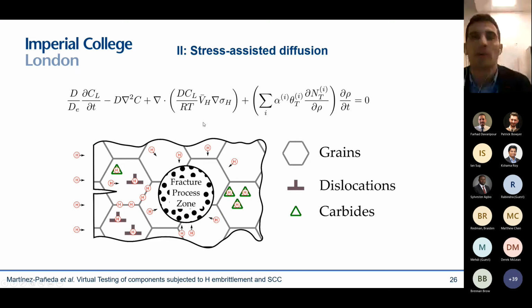But in reality, we know that metals are not perfect. They have defects. So hydrogen not only travels through the metal, but also likes to sit in maybe carbides, dislocations, grain boundaries, and other defects. So one can, and we have done that. We have developed extended models that account for multiple traps, so we can predict exactly what is the partition of hydrogen, what is the hydrogen sitting, basically.